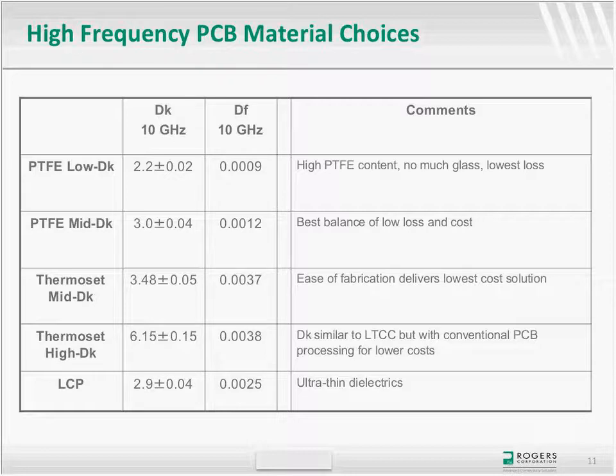Because they are very high in resin content, they tend to have higher z-axis expansion values, and this could be a concern depending on how thick a multilayer might need to be for the application. So that is something that we always tell people: when evaluating these in a multilayer structure, care should be taken in doing the evaluations for plated through-hole reliability.